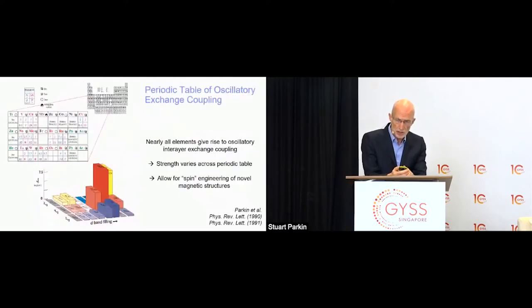And also, I demonstrated that this is a property of nearly all elements in the periodic table, all metallic elements, all the transition metals, whether they're 3D, 4D, or 5D, and all the noble metals, copper, silver, and gold. Each of these materials has a distinctive response to a magnetic impurity or a magnetic layer, which gives rise to this long-range magnetic coupling. And it varies in a highly systematic way as we fill the D bands in these 5D, 4D, and 3D metals. And you can see from this plot of the strength of this long-range magnetic coupling mediated by this spin density wave that the strength is strongest as you increase the D band filling.